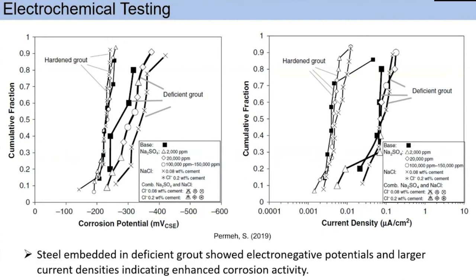These are results of electrochemical testing. This one is corrosion potential and another one is current density. In the first, corrosion potential, the deficient grout in the upper duct elevation had more distinct differentiation of negative active potential. And in current density, the steel embedded in deficient grout in the upper elevation of the specimen was consistently and distinctly higher than in the hardened grout that formed in the lower elevation of the specimens. In the presence of deficient grout, corrosion is enhanced, with more electronegative potential and higher current density in deficient grout.